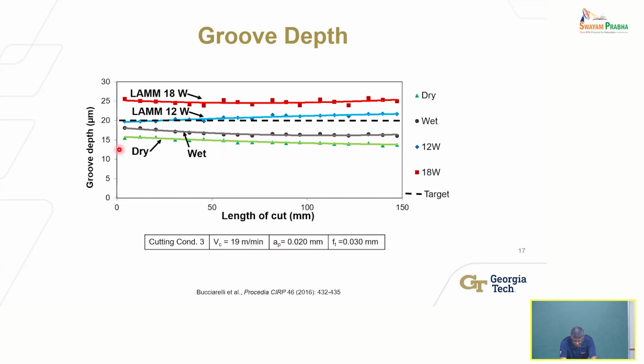What do we see? If you use dry, we already saw the cross section, there's deviation there. You can see that we only generate about 15 microns for the depth of the groove, which means that there are different contributing factors to this. One of which I have not talked about is that for these very small tools, you have to determine where the zero point is before you program.